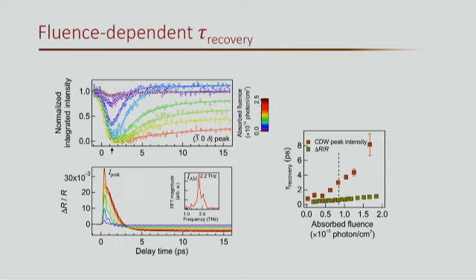So is the reflectance measured at a particular wavelength, or is it just broad reflectance? It's measured at a particular wavelength. Okay. How did you pick that, or does that matter? It doesn't matter in terms of recovery time. It matters in that for different probe wavelengths, you can see different proportions of the coherent oscillations because it couples to different phonon modes with different Raman matrix elements. But we actually also do a white light broadband probe, and at all wavelengths we see this very strong suppression signal.